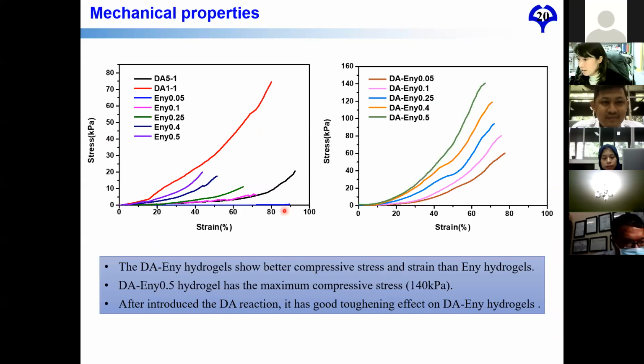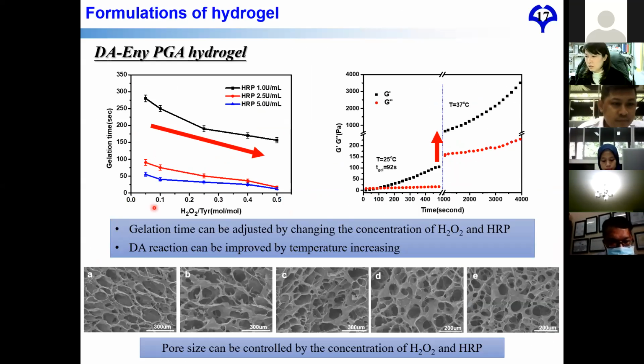In this slide, you can see that we can also control the gelation times by changing the concentration of H2O2 and the HRP. If we increase the HRP concentration, the gelation time will decrease. And this line is the reaction after we add the Diels-Alder reaction. It can also be seen that after increasing the Diels-Alder reaction, the storage modulus of the hydrogel will increase. And we can see that two kinds of network are introduced into the hydrogel.